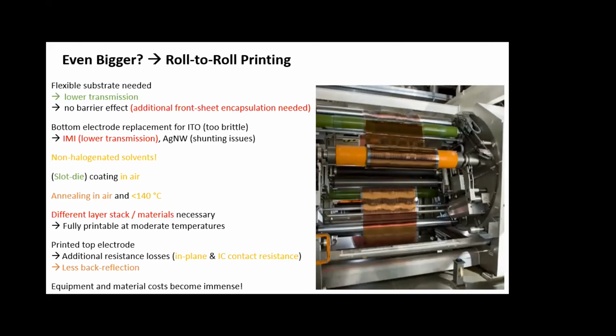One thing is the change of the substrate, which transmission-wise is not a big problem, but all of a sudden you don't have glass anymore, which means you need an encapsulation, an additional layer to your substrate on the front contact. Also, you cannot use ITO anymore because it's too brittle. You need structures like IMI, which are less transparent, or silver nanowires, which cause other problems. Non-halogenated solvents, obviously, due to legal reasons.